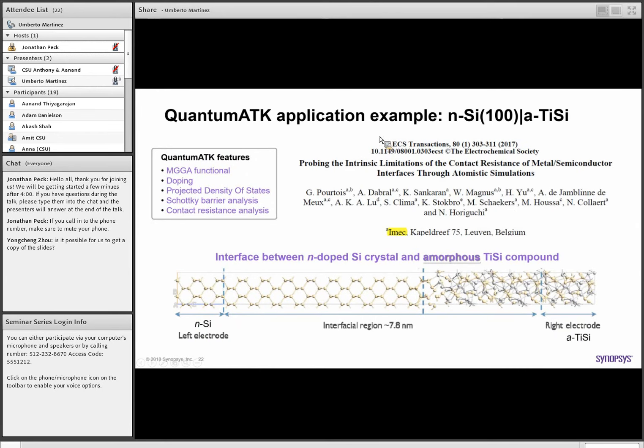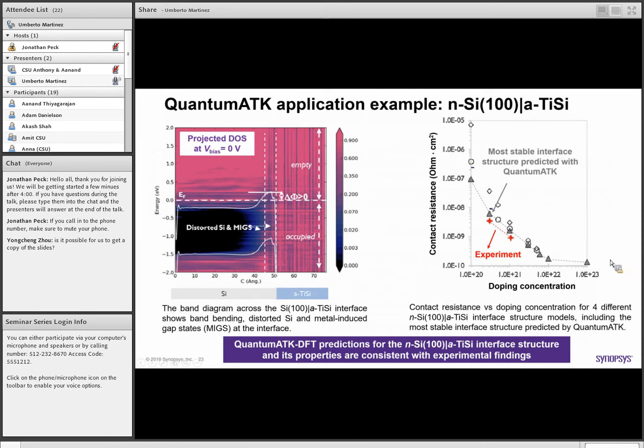This is another nice example from IMEC that shows the interface between silicon crystal and amorphous titanium silicon compound. And I want to highlight this specific interface because it shows that you're not limited to studying crystalline structures. So you can also have an amorphous compound, an amorphous system, or an alloy on one of the two materials, which is very relevant for your applications.